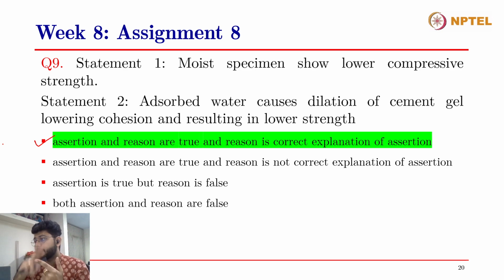Because when you carry out a strength test in a dried specimen, the strength that you'll be getting is higher, right? Because there will be no adsorbed water, and therefore the dilation will be less, the cohesion will be much higher, and the strength will be higher. Why do we want to do a strength test in a moist condition? Because there are two reasons to this.